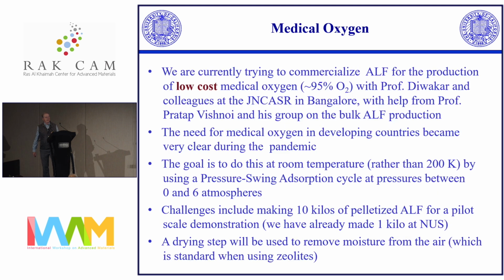But we're looking now at medical oxygen. You'll all remember during the pandemic how there were shortages of medical oxygen all over the world, and especially in developing countries, because lots of places in rural areas don't have access to cryogenic distillation. The availability of the lithium-based systems is not great, and of course, lithium's very expensive too. So we're looking, with colleagues at the Jawaharlal Nehru Center in Bangalore, at the possibility of producing low-cost medical oxygen. Medical oxygen typically would be about 95% oxygen, and our separation is so good that the purity is not going to be a challenge at all.